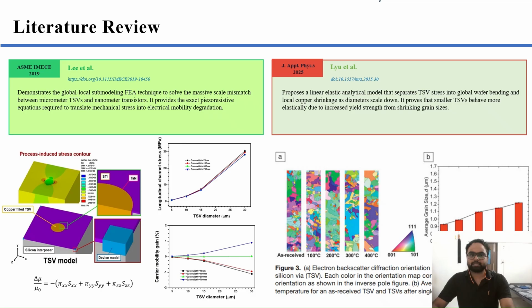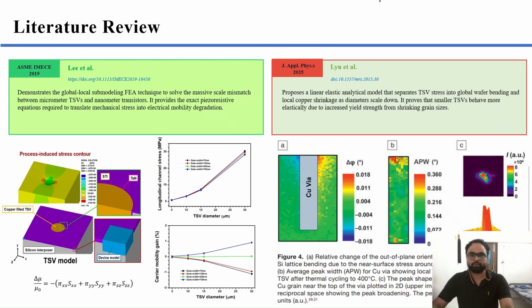Why does it matter? Large grain means lower yield strength. The copper becomes softer and more prone to permanent deformation under TSV stress. This directly explains why processing temperature makes the stress situation worse. These three panels show what X-ray techniques reveal about the damage inside the TSV. In panel A, the color map shows how the silicon crystal lattice is slightly tilting or bending near the copper wire. The orange and the blue at the top indicate the silicon is being pushed and pulled by the copper thermal expansion. Panel B shows the copper itself.